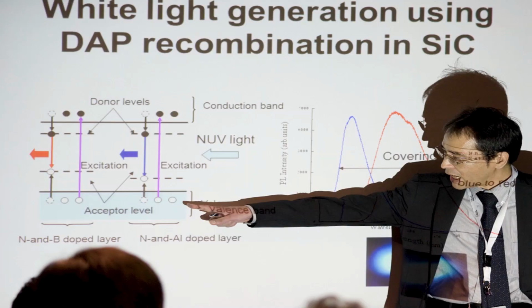Okay. Then, a few years later, came Satoshi Kamiyama, who proposed a new type of white LED for general lighting. If you have donors and acceptors, then you can have a recombination from them. And if you do this in silicon carbide with a certain polytype, 6H silicon carbide polytype, and you do it in 2 layers with different acceptors, you get 2 different levels where there are transitions.